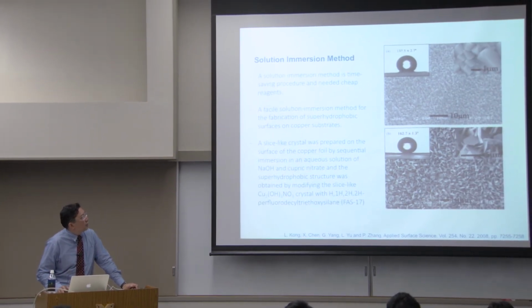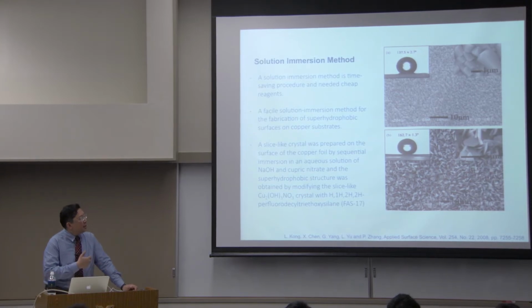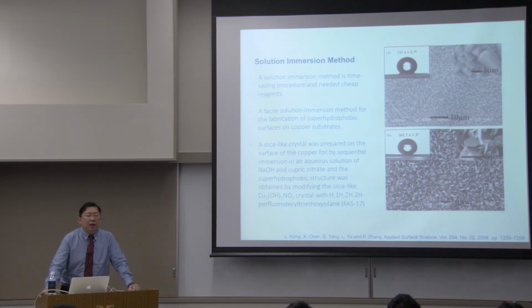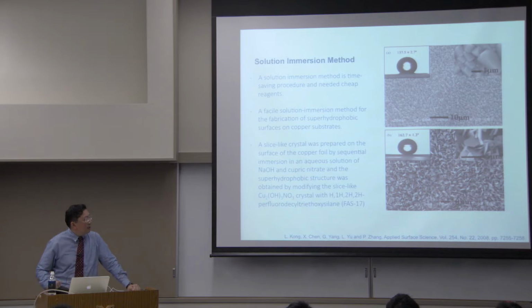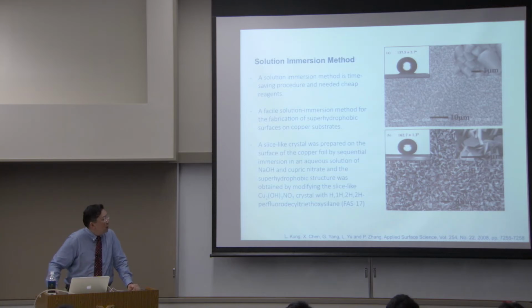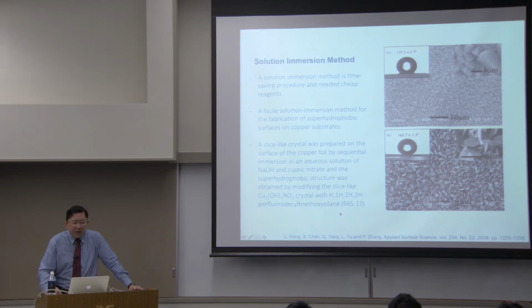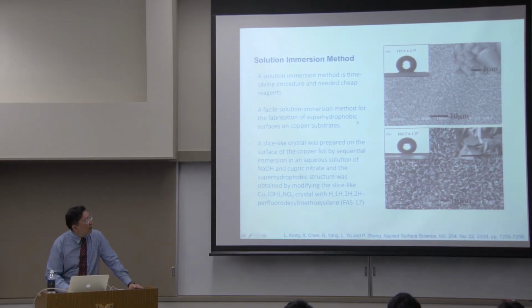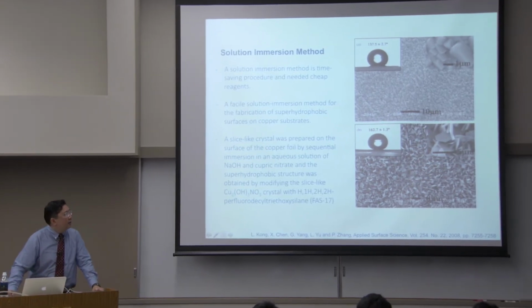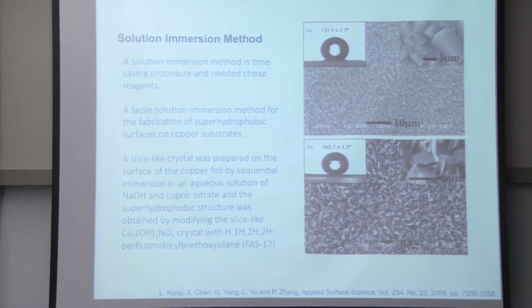Solution immersion method. This time the procedure is inexpensive in that the surface of a substrate can be modified by different solutions, usually with aqueous dipping in sodium hydroxide and copper nitrate. As you alternate the copper foil between these two solutions, you end up etching and providing this rough structure. Again, this was modified with the use of perfluorodecyltriethoxysilane to produce this superhydrophobic effect. In this case, a contact angle of about 160 to 163 is even observed.